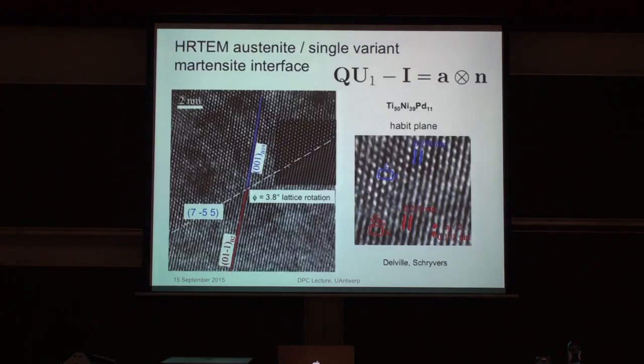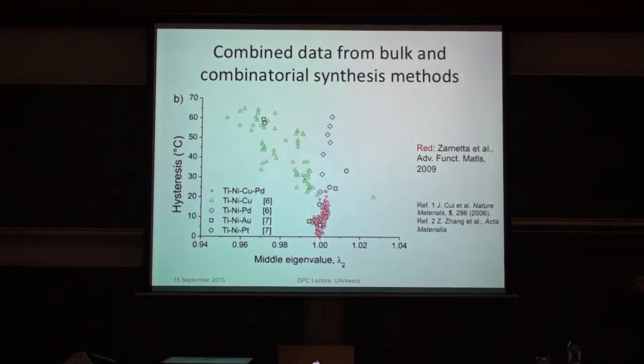And somehow, I have a close-up of this. There's alloys down here with 1 and 2 degrees thermal hysteresis, which were not known, or largely not known, certainly among big first-order phase transformations before this.